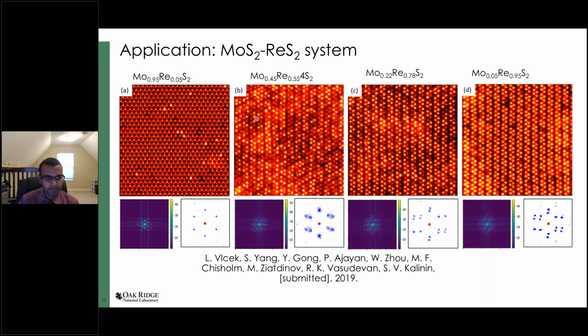But once you add a particular amount of rhenium, in this case about 55%, you can clearly see there's a structural phase transition that occurs, and it gets stronger, and you can clearly see these kind of columns that are breaking out within these images. Now, with this paper that we submitted, a lot of it was to show that the local structural distortions come from not the global concentration, but rather the local chemical concentrations, but that's neither here nor there. So the point is, we have these images, we can look at the local distortions, and we can isolate which of the atoms are molybdenum and which are rhenium, and then we can create different models and compare which model is more appropriate for our particular case.